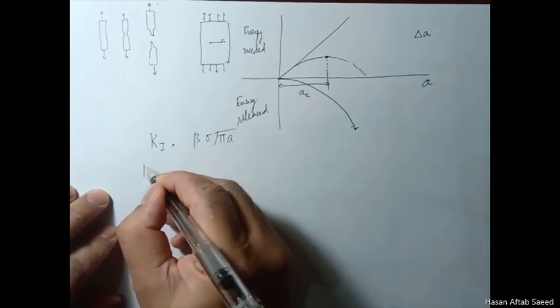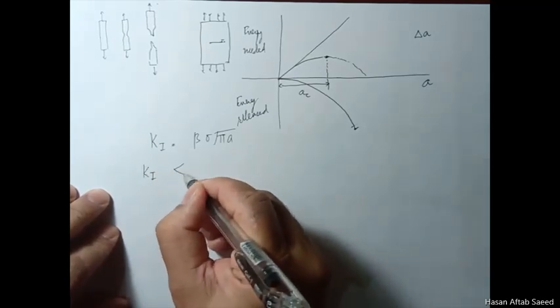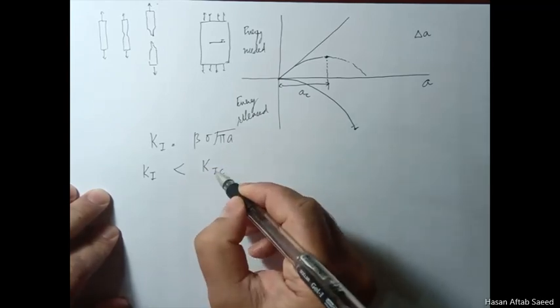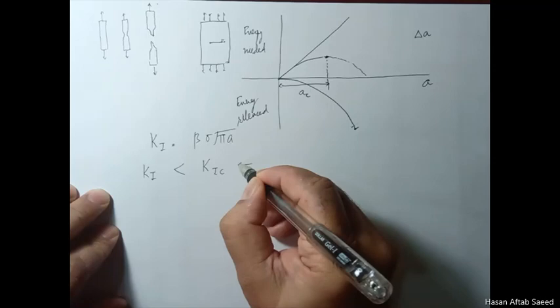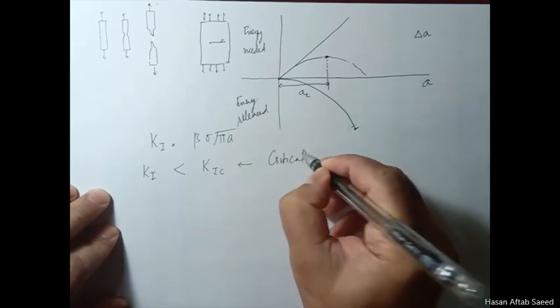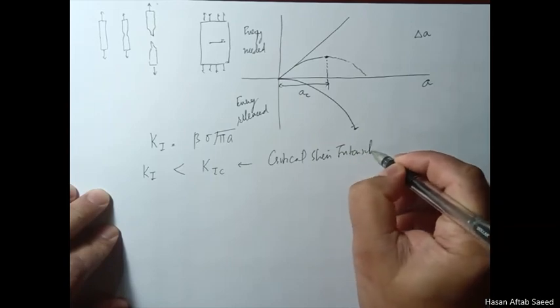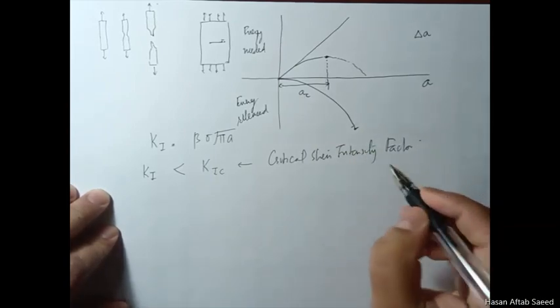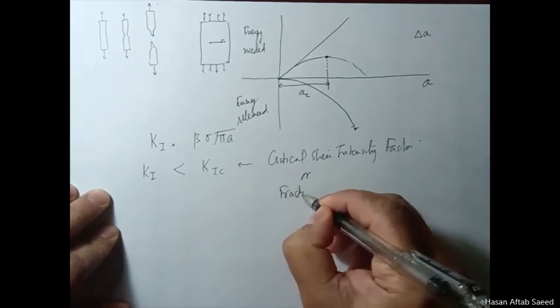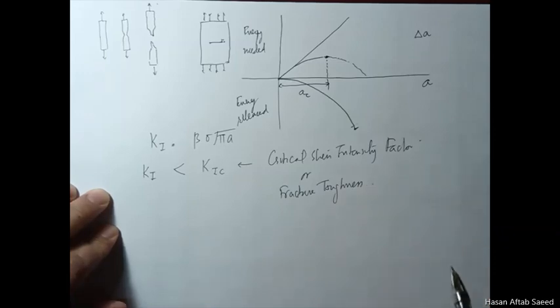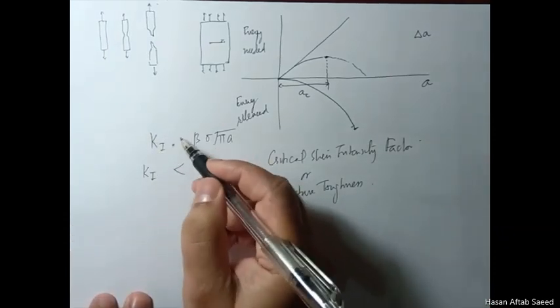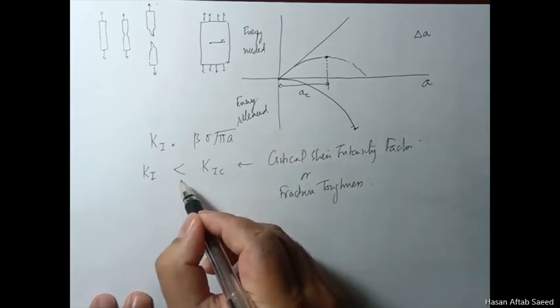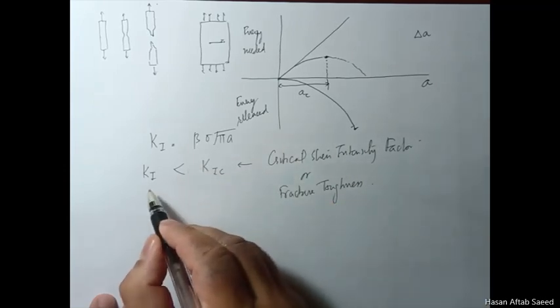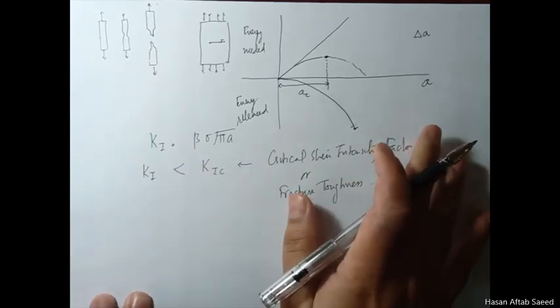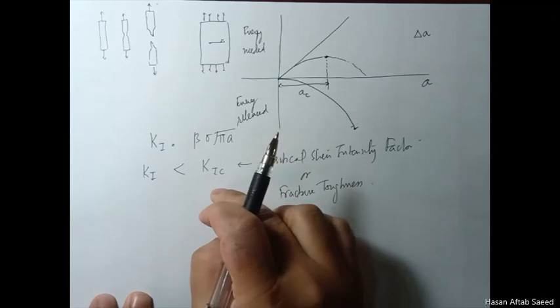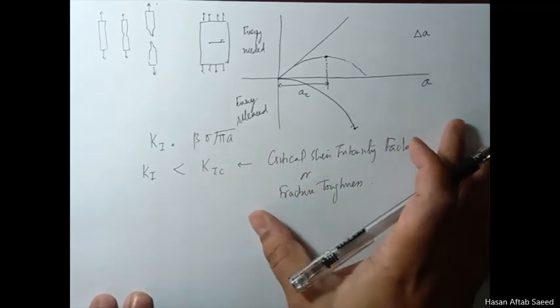Here we will compare K1 to something called K1C, which is the critical stress intensity factor, or sometimes called fracture toughness. If this K1 for any situation is less than the K1C, the crack will not run away, so it's safe. But if it becomes equal to K1C, it will not give you any warning, it will just break.